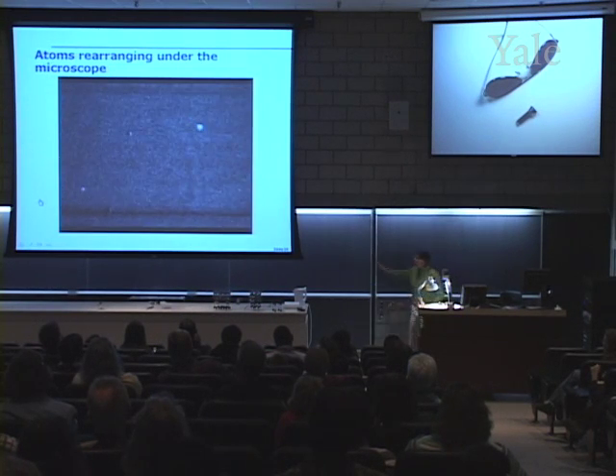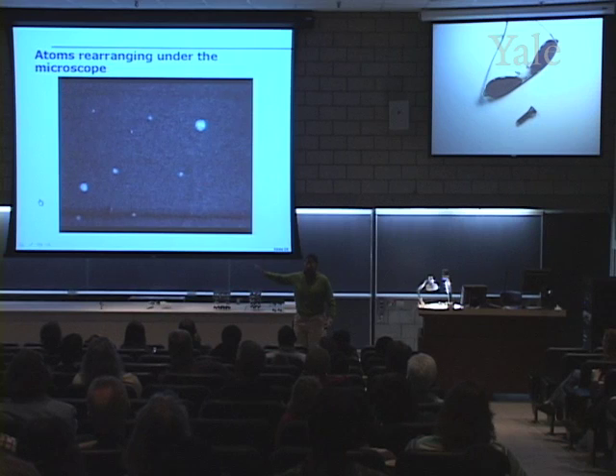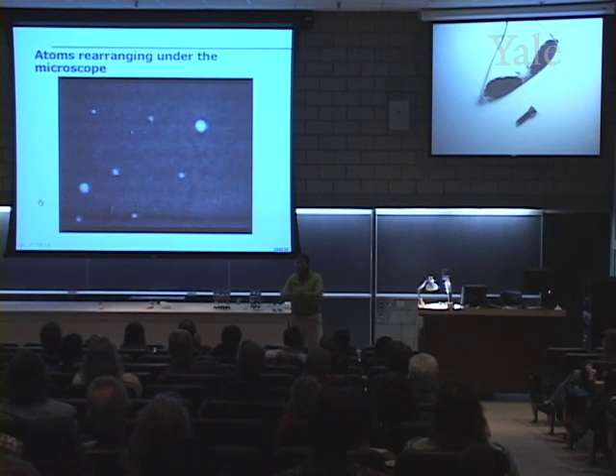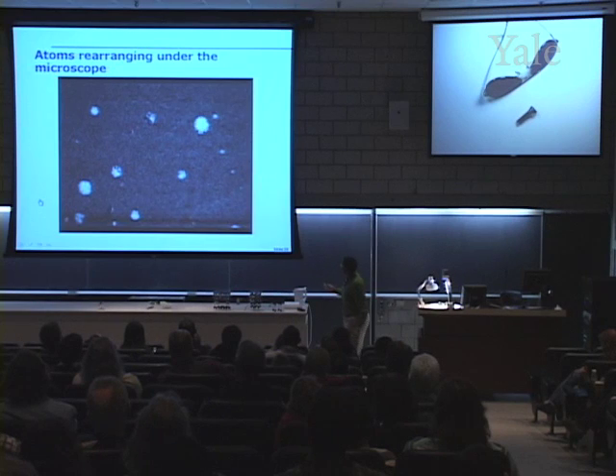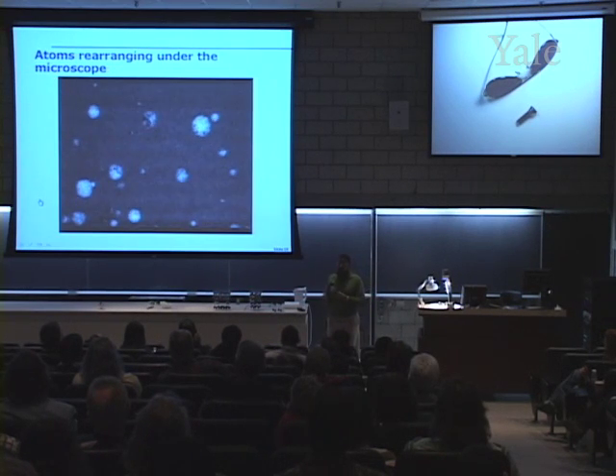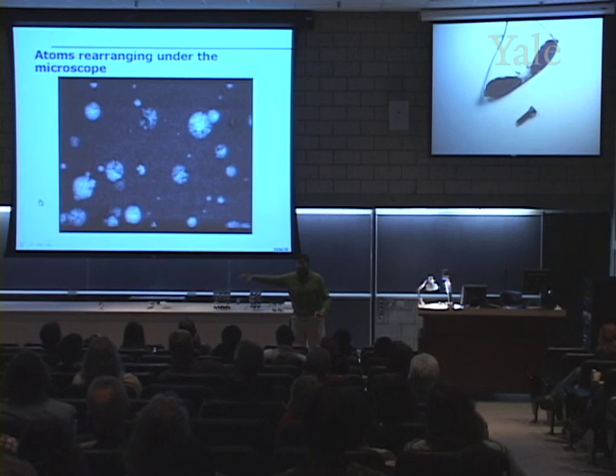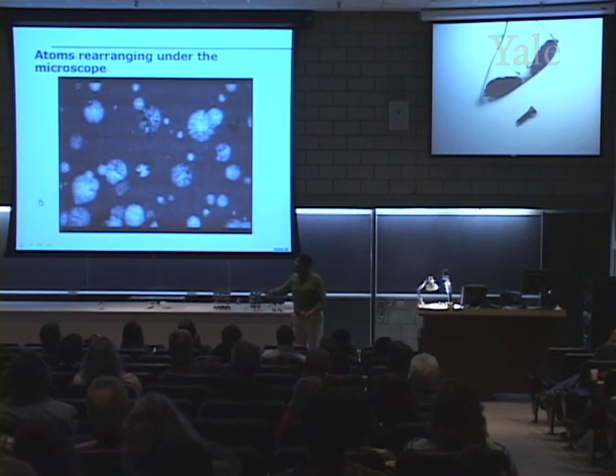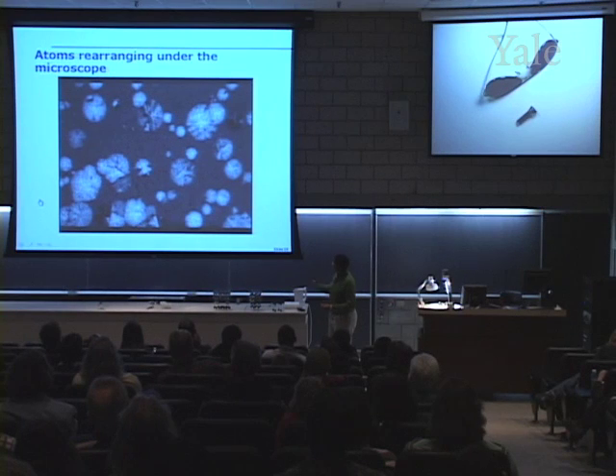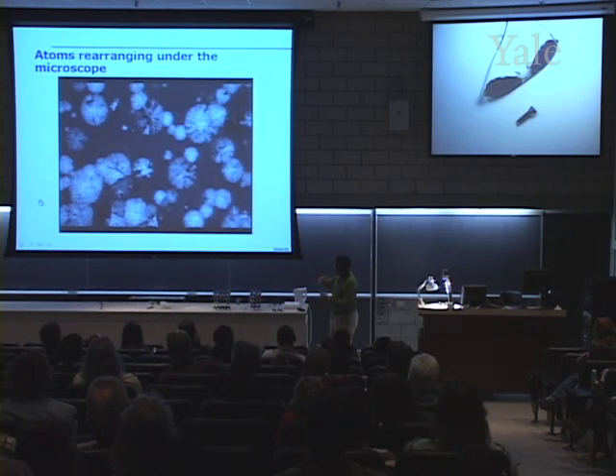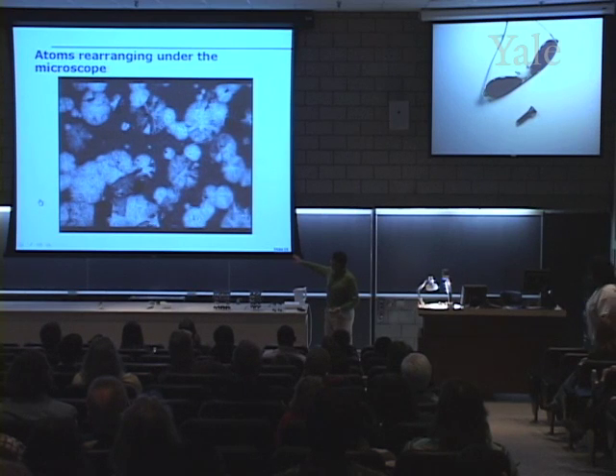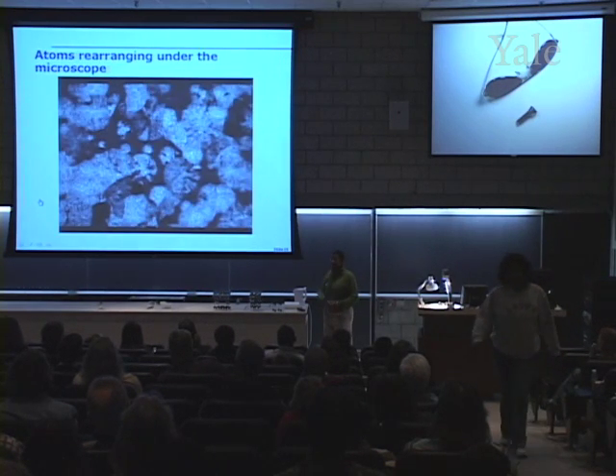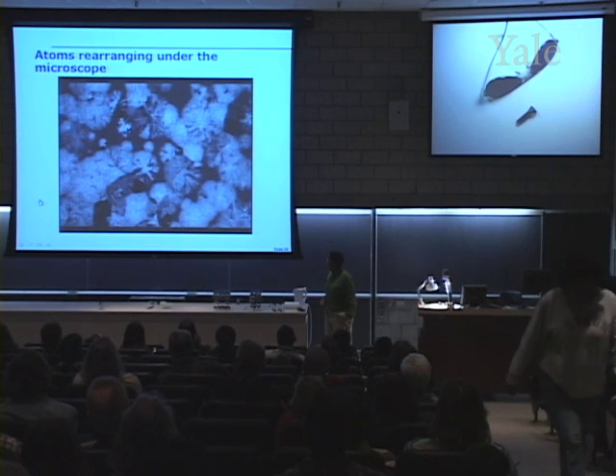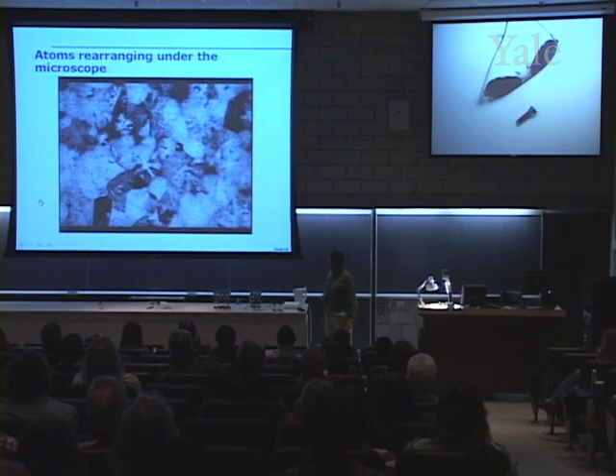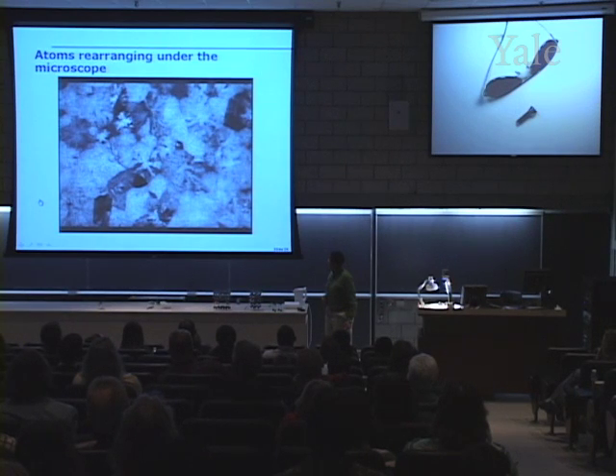So you can see in this very gray area, we essentially have an amorphous material, meaning we don't have atoms in any kind of arrangement. But you're starting to see these white dots. Those are small grains. Inside of them are atoms that have a periodic arrangement, sort of like that marching band again, but they're in a structure of austenite. And we continue to heat this material until all of that area is covered with these grains until it's fully crystallized. All right, we're still baking. We're still baking. Ding, time's up. All right, so this is baked.